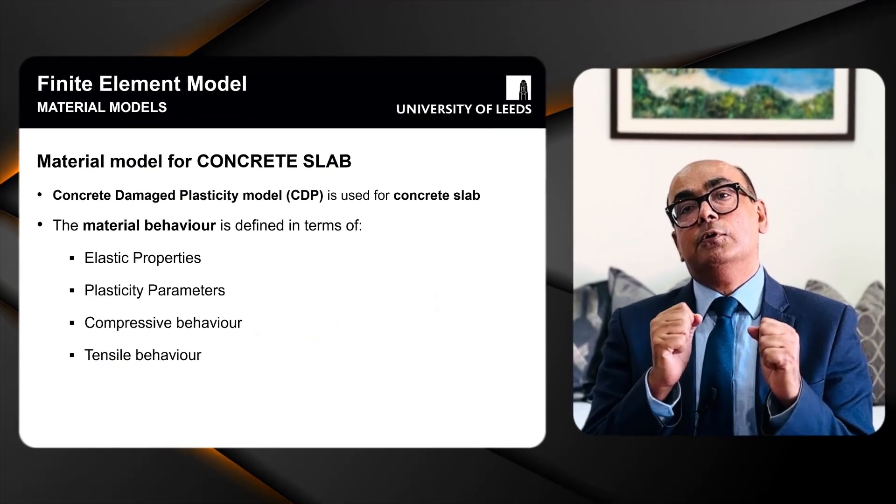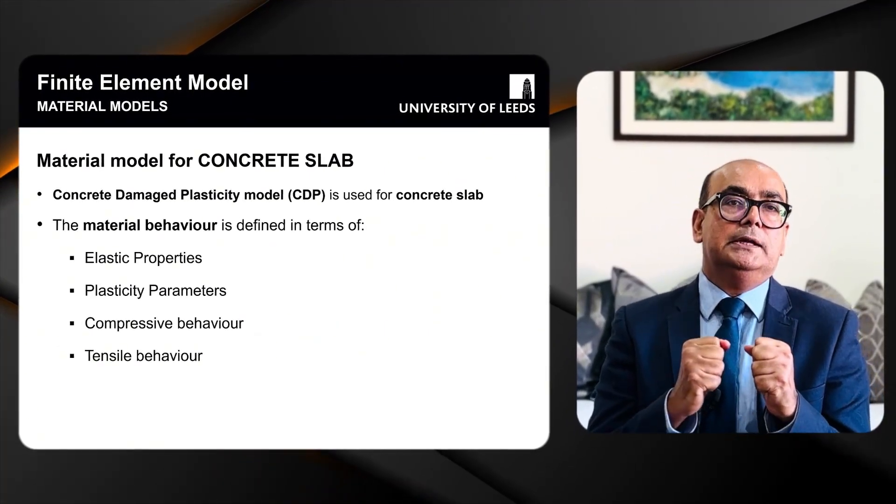The material model for concrete is very important. I tried different models such as the Drucker-Prager model, elastic-plastic, and various others, but they did not give proper results. Concrete Damage Plasticity (CDP), on the other hand, can model both concrete crushing and concrete cracking. Cracking is really important here, which is why I used the Concrete Damage Plasticity model.